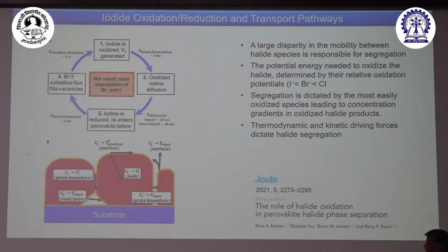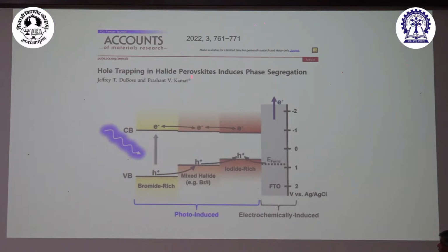Okay, so this is a perovskite perspective given by Barry Rand, which essentially supported our theme that iodide is oxidized and then the oxidized iodine diffuses, and most of it regenerates, but a small fraction can just get out and form iodine vapor. Okay, so that is where we stand. That's the article, if you want to study how this process occurs, that we published in Accounts of Materials Research: Hole trapping in halide perovskites induces phase segregation. So basically you have this electron-hole transport, and because of this gradient structure, they move to the lowest-bandgap, iodine-rich area, and that's where you start seeing the problem. So this is now, everyone agrees, one of the problems for perovskite instability.